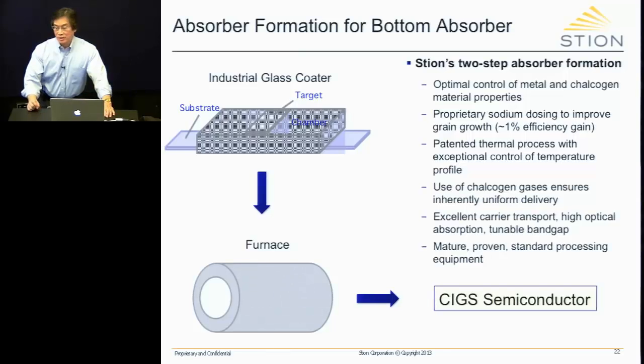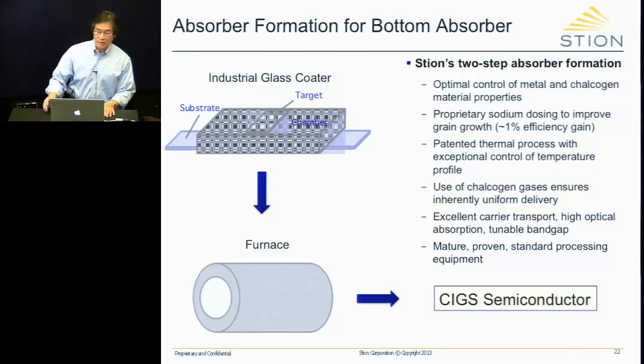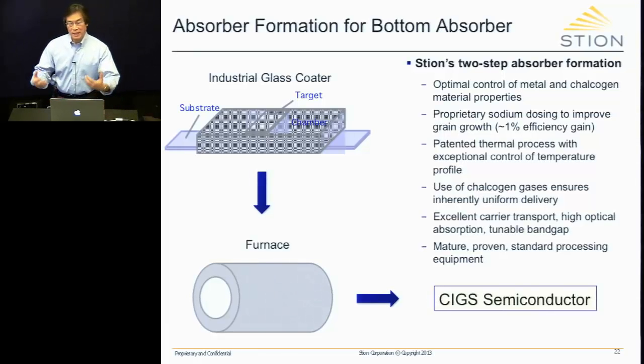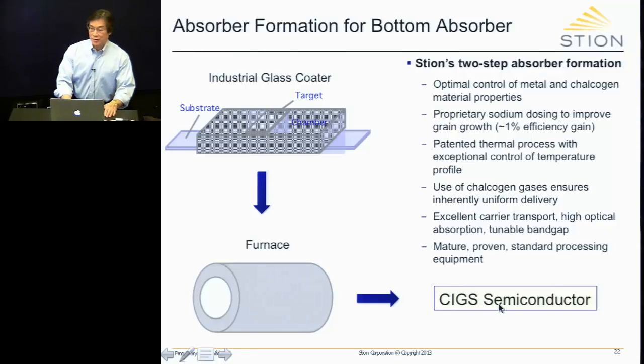Therefore, you can see that this is a much better situation because you can sputter very accurate, very precise thicknesses. This is nothing that you have to invent. People know how to do this over very large areas as well. So after you deposit the metal precursor, you put that into the oven and you reactively anneal it. You do this in a hydrogen selenide atmosphere, or a hydrogen sulfide atmosphere, or a selenium atmosphere, or a sulfur atmosphere. So you stick it in the oven and you bake it, and out comes the CIGS semiconductor that we use for the bottom device.